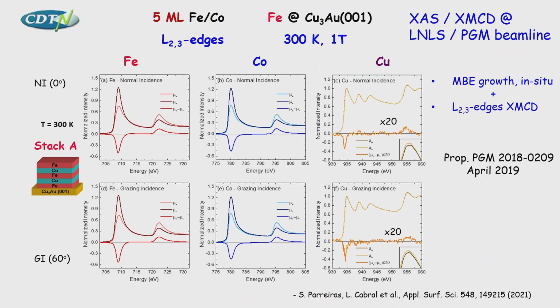Okay? And to try to understand this system more, we went to the synchrotron, okay? And we did XMCD. Then what you can do is element specific measurements. We can measure the magnetism at the different edges, iron, cobalt, and we also did the copper edge. And we saw also dichroism in the copper. That means copper is magnetic in this material, okay?